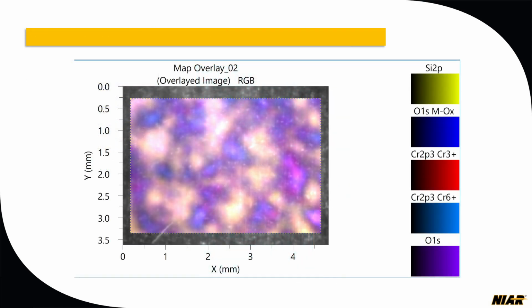The other aspect is an overall map where we have some silicon. Again, it might be just material handling because this sample was just received, and I'm assuming some kind of oil was on the material. So that's why we're detecting silicon. The other aspect is the Cr3 and Cr6 distribution that you're seeing overall, and the oxygen percentage. So that is a combination map of what you're seeing. So this is one of the defects.